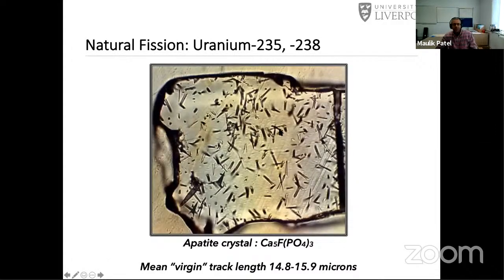Some of the natural fission tracks are also seen, because you have spontaneous fission going on in minerals, and that leads to these ion tracks as well. The simple reason you see contrast is this: if you take a glass and pulverize it, make it powder, it's no longer transparent, it becomes opaque because you have created defects. And for the same reason, you see these color contrasts in optical micrographs and in electron micrographs, because light cannot pass through, as the atoms in those places are displaced or have a changed refractive index.